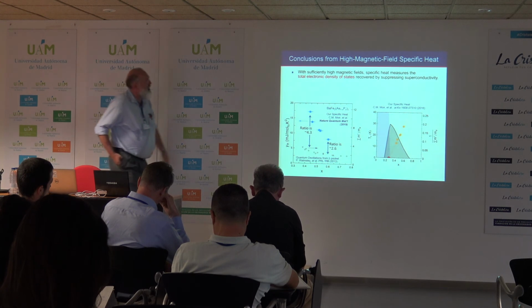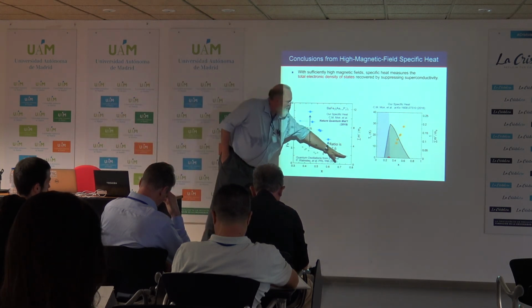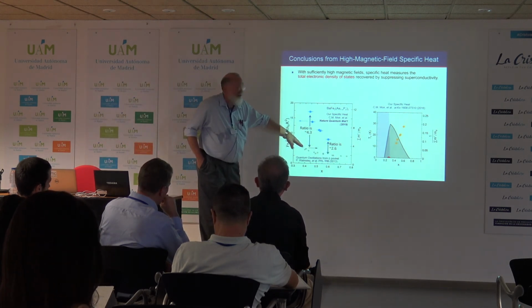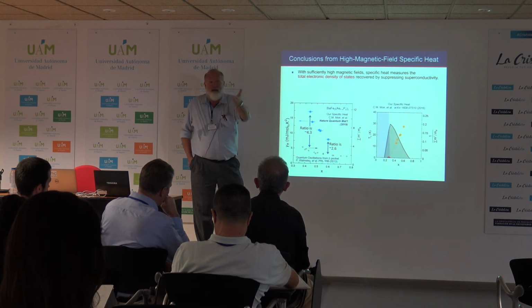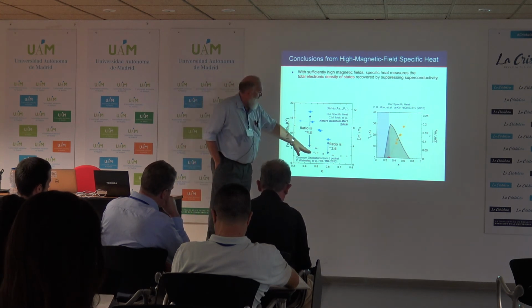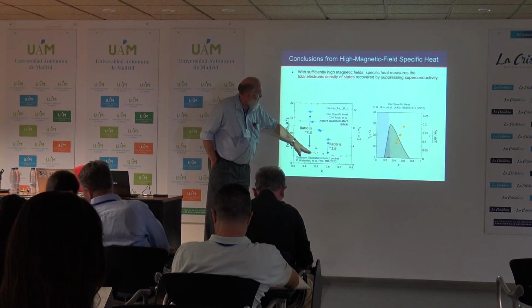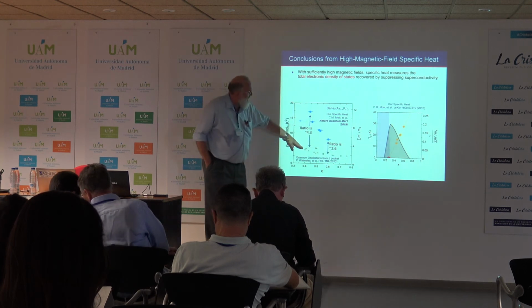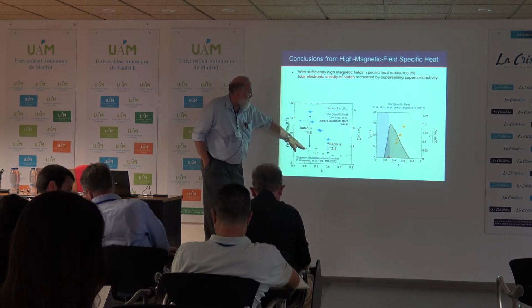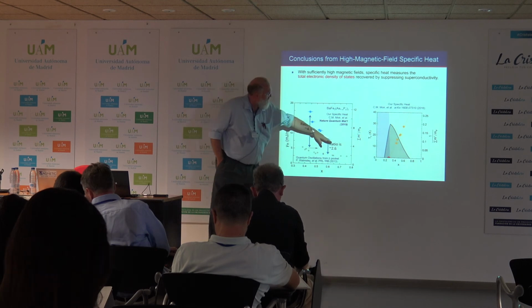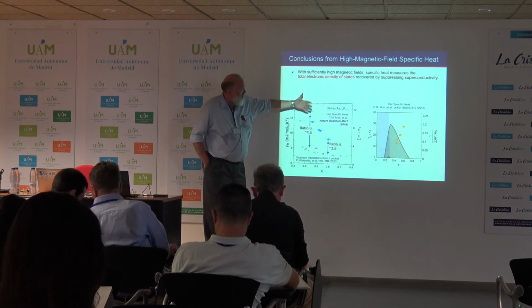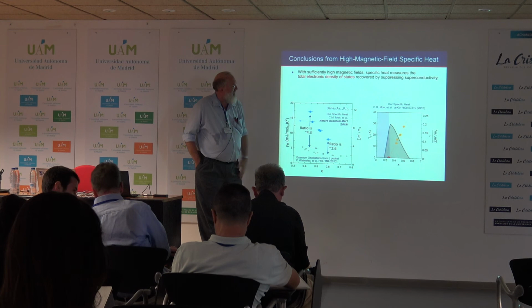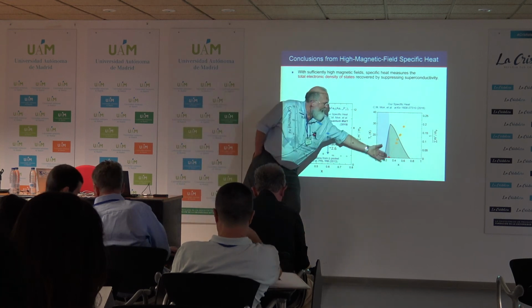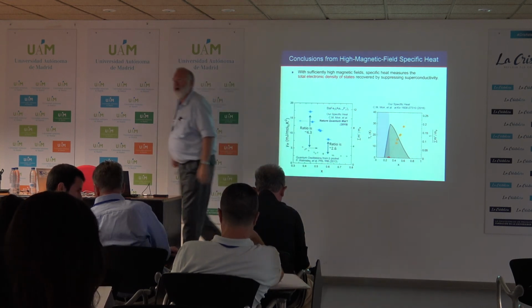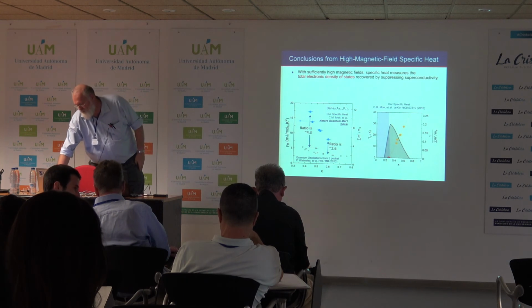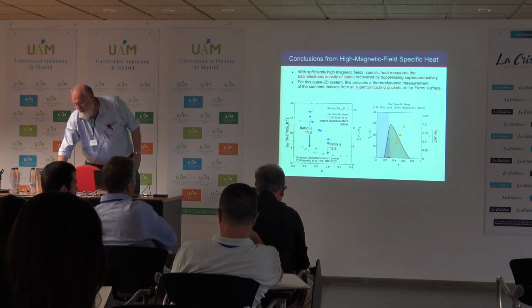And so just to summarize, mass divergence was first seen in quantum oscillations and specific heat jump in Tony Carrington's group at TC in the case of the specific heat jump, and then in the beta pocket in high field quantum transport measurements. We're doing specific heat measurements looking at all the pockets. We also see a mass divergence, and in this case the mass divergence also seems to occur right near optimum doping, as was reported by Tony Carrington's group.